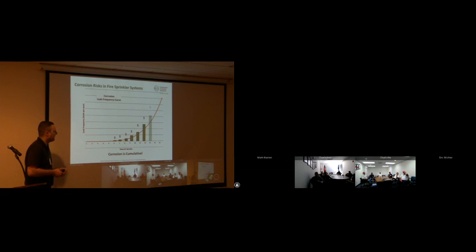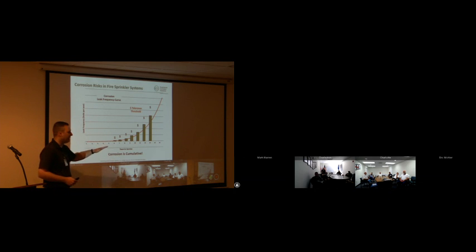This is what we were talking about earlier, the leak frequency curve. Once again, this is to illustrate corrosion is cumulative. Once the metal comes off the pipe, we can't ever put it back on. There's nothing we can do. We can only stop the corrosion at some point and preserve what pipe wall is left. So every time we repair a leak, enough oxygen goes in to create another leak, our leak frequency goes up, and our expenditures to maintain that system go up.